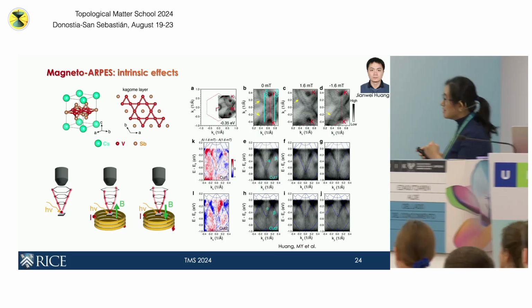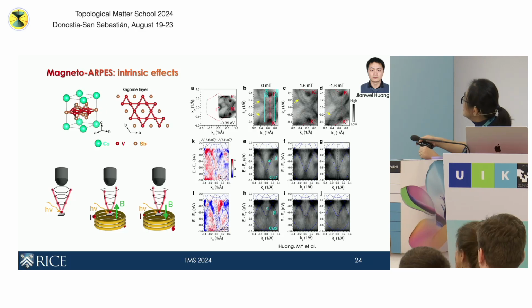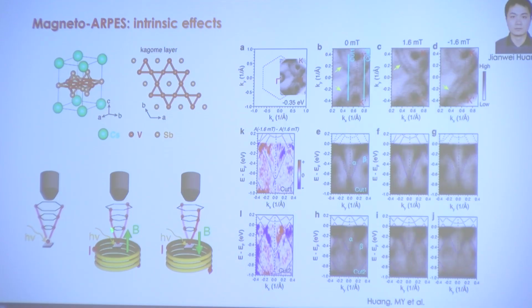So we look at this material with the field. We compare the no field, plus field, and minus field. And just to show you some of the effect, this is a measure of the Fermi surface. This is a measure of the constant energy contour taken about 350 millivolts below the Fermi level. What you see here, this is the Brillouin zone. These are the triangular sheets that are associated with this Van Hove singularity.